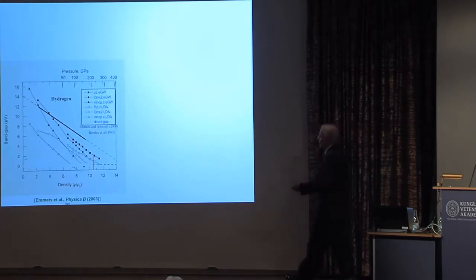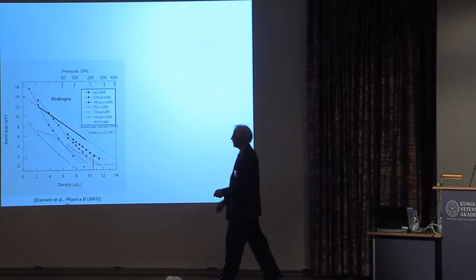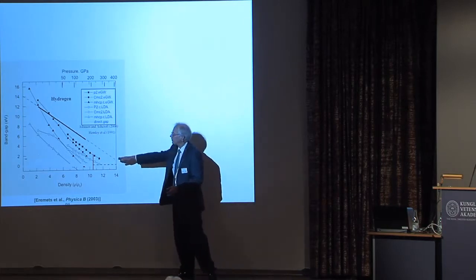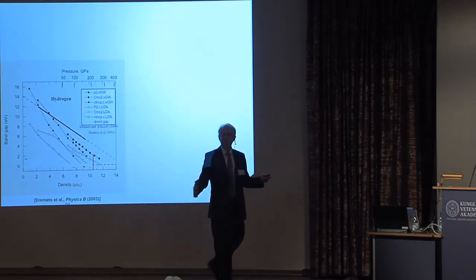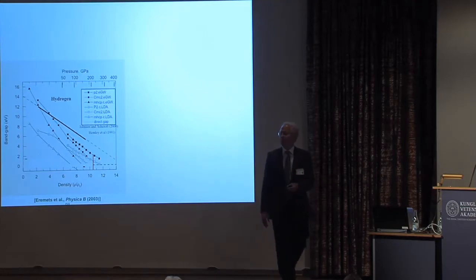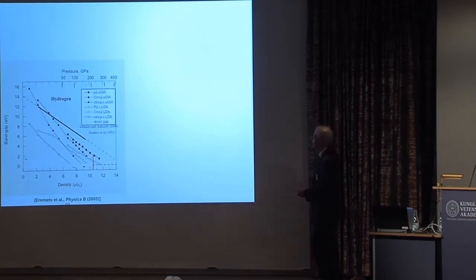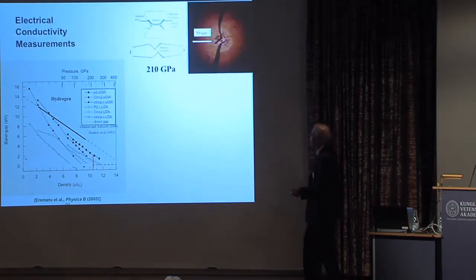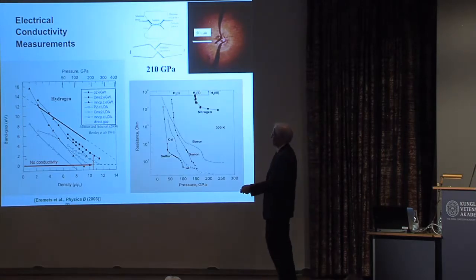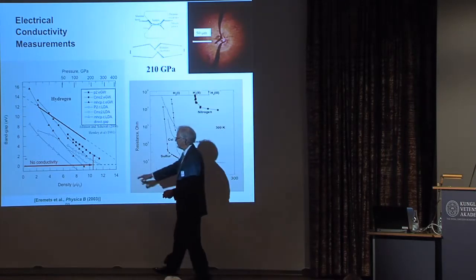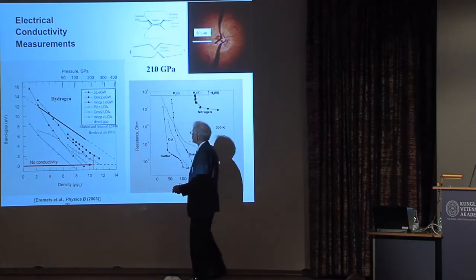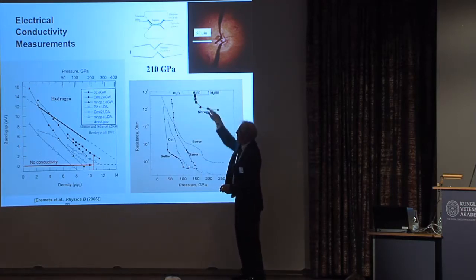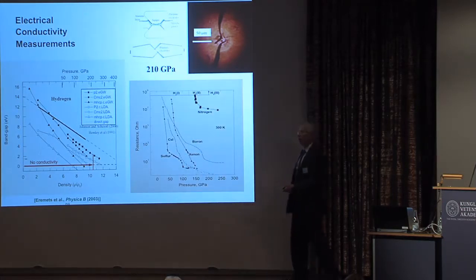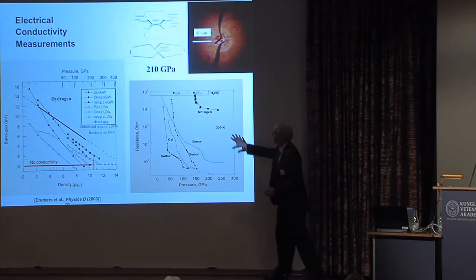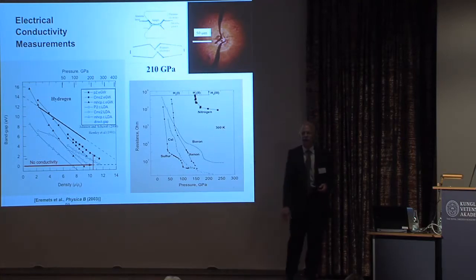Well, it turns out that a number of theoretical calculations all predicted at about 150 gigapascals that there should be this metallization where we see this transition to phase 3. When we do electrical conductivity measurements, we find, in fact, that it remains an insulator or at least a semiconductor up to these pressures. So it is not a metal over that range of conditions, in contrast to what we see in these other elements, some of which are superconductors.